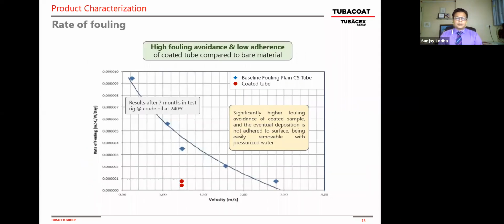This is a study done on the rate of fouling by a major US refinery over a period of 7 months using crude oil, a heavier feedstock. What you see on the screen here is the rate of fouling at a given velocity. The blue dots are for the baseline carbon steel tube, and the red dots were taken at a given velocity of 1.2 meters per second. You can see there is significantly higher fouling avoidance on the coated sample, and any eventual deposition does not adhere to the surface because it's very easy to remove. You can see a difference of as much as, on the high side, 4 times reduction in the rate of fouling for the coated tubes.